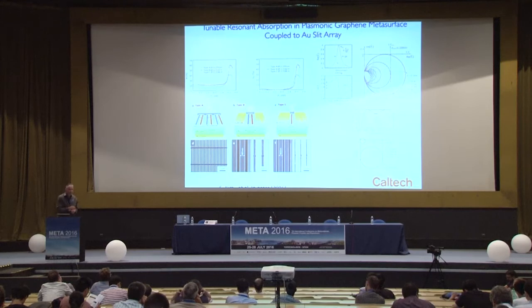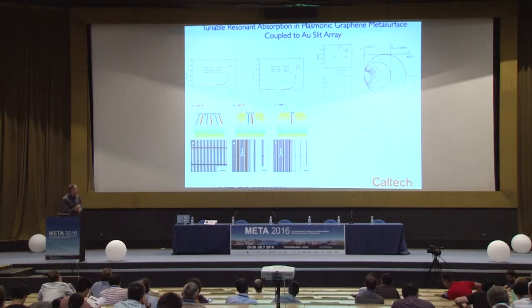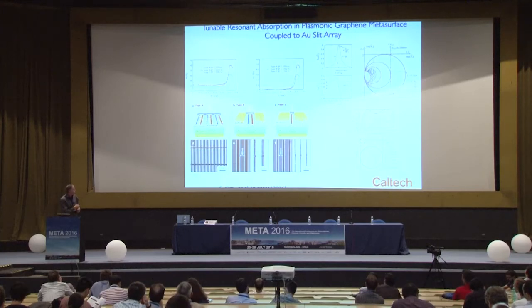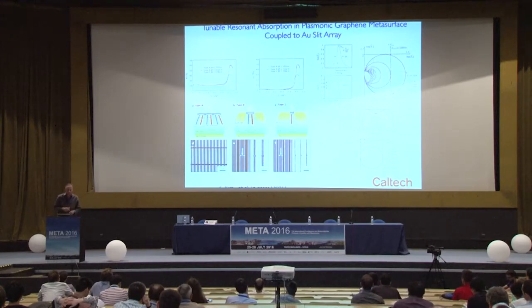This is something that's been a holy grail among the people in this field for some time. And this careful matching of surface admittance allows us to get very close to this number. And as we change the Fermi level, you can see here the absorption modulation efficiency and the actual absorbance itself, which is changing from about 25% up to 70% as we change the graphene Fermi level position. So we can see very, very strong modulation of the absorption properties of even a single monolayer of graphene if we appropriately tune the admittance.